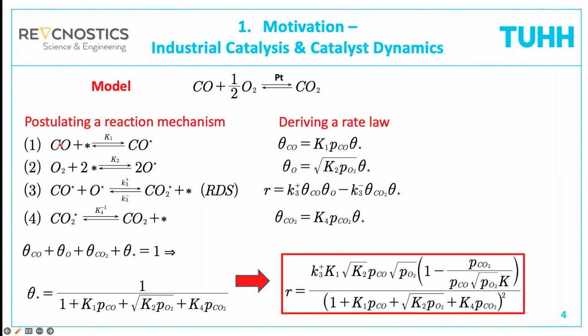And now we assume here in this case, for example, that CO adsorbs to an active site, and then we have adsorbed CO. And this adsorption desorption processes are so fast that this step is quasi equilibrated. And then we have here the oxygen adsorption, which occurs dissociatively. So we have oxygen atoms also quasi equilibrated. Then comes the surface reaction, which is, if the temperature is not too high, the rate determining step. And then we have the desorption of the product. So what you please keep in mind, we have to postulate a reaction mechanism, and we assume that we have one kind of active site, which is typically unknown. That's why we use the little star. And now we have the problem that we cannot really measure the adsorbed species on the surface of the catalyst. So we have to relate them to something that we can measure, and these are the partial pressures in the gas phase.